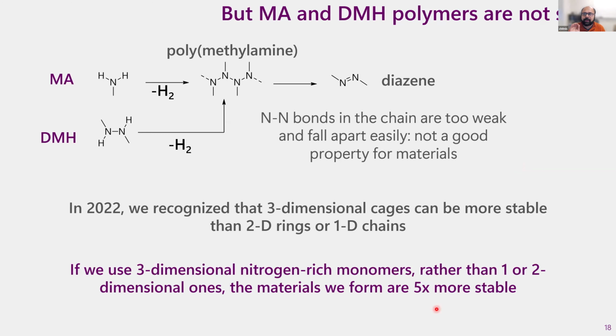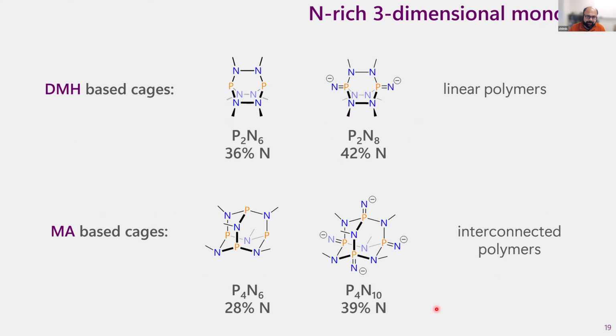Because now, for the first time, humanity has access to nitrogen as a building block. We never used it as a building block before. This is unlocking a new resource. So this is what the cages look like. Again, you don't need to understand any of the chemistry. Just look at the numbers. These cages are 28 to 42% nitrogen by weight. And they do not blow up. They are extremely stable. For comparison, TNT is 21% nitrogen. And that famously blows up. So even twice the amount of nitrogen, and they are still stable.